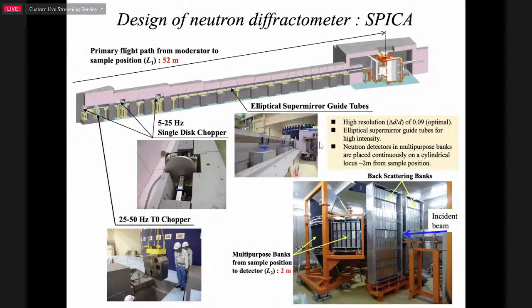This slide shows the detail of the neutron diffractometer SPICA, which was designed and built by ourselves. It is located about 52 meters away from the neutron target, here. The long flight path is essential to realize high resolution on the diffraction data. The resolution is about 0.09, like this. In addition, a high-grade elliptical supermirror guide tube has been installed to get high intensity. So, a very long guide tube to get the high intensity. This is the overall neutron diffractometer SPICA.